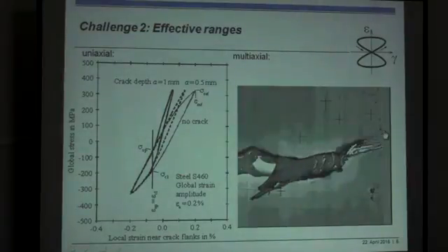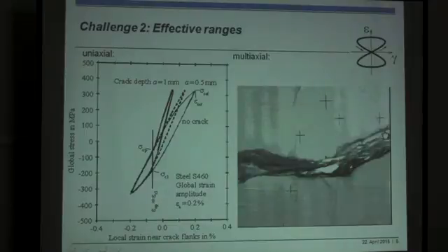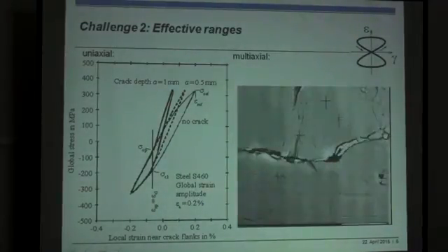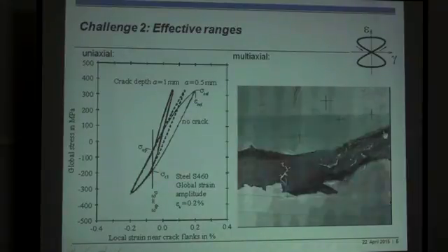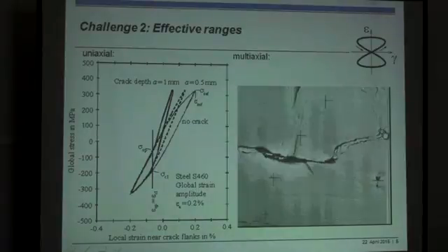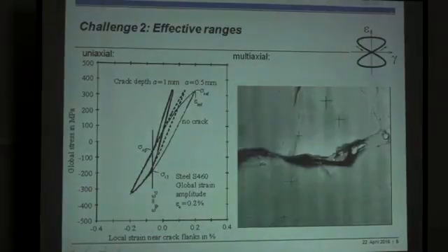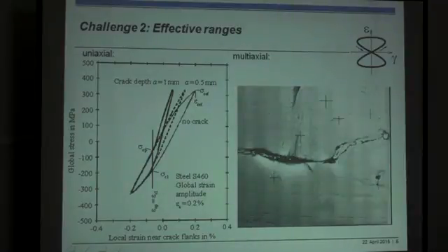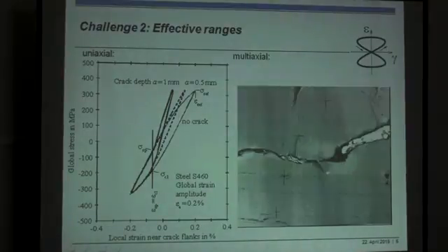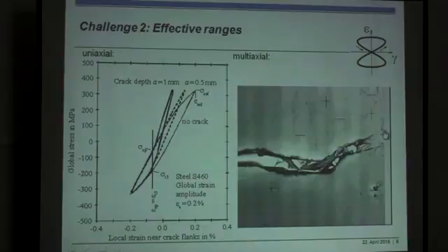Now the crack is closed, and while the crack is closed, you see hopefully that there is some horizontal motion of the lower half of the material against the upper half of the material. So although there is closure on the, let us say mode 1, it's not completely mode 1 here, we have a mode 2 component which could be able to drive the crack longer.